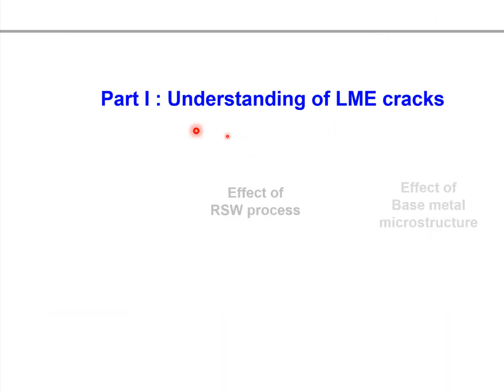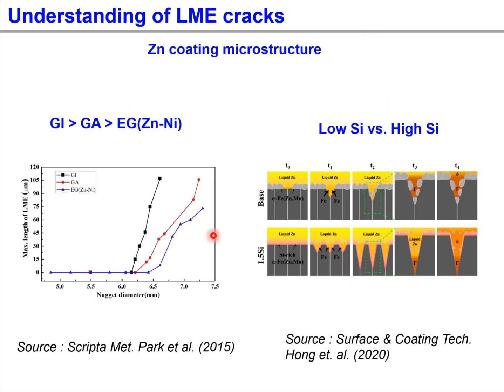In part 1, let's make a deeper understanding of LME cracks. Firstly, the effect of zinc coating on LME cracks. In the year 2015, we made an investigation of the effect of different coating types on LME cracks. We made resistance spot welds with increasing current, which results in increased nugget diameter. Then we compared the maximum LME crack lengths at the same nugget diameter. The result shows GI coating is most susceptible, then GA coating, and lastly EG coating.